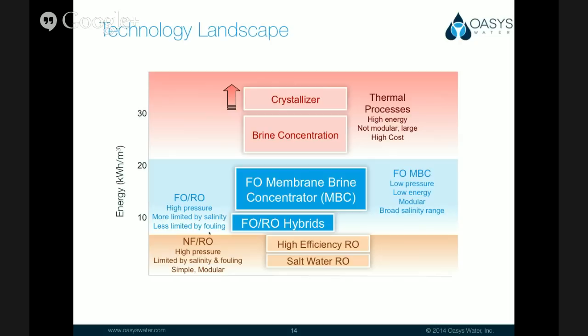So I'll contrast that with the middle ground here in forward osmosis. And what you can note is that certainly forward osmosis and reverse osmosis hybrid systems implicitly have a higher energy demand than a standalone reverse osmosis process. Basically, it's entropically unfavorable to pull water into a higher salinity environment and then extract that with RO. So from an energy side, you certainly will pay a penalty in that separation.